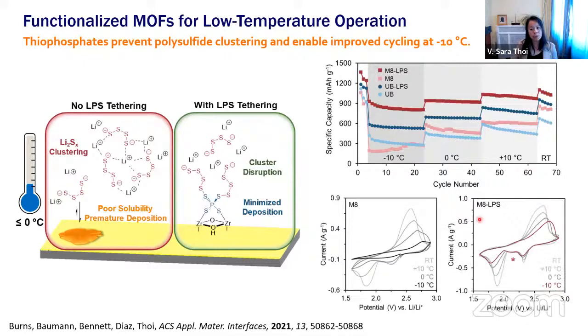But if you have the functionalized material, you start to see another phase or another reductive potential here that may indicate that we have some sort of phase differentiation that's occurring because of the thiophosphate in our material. And so this might again indicate that we are seeing some sort of clustering effect or disruption effect that may be enabling us to have higher specific capacities in our materials.